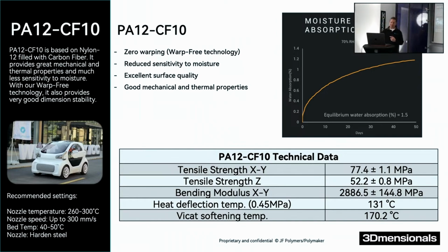So then moving down, then we have PA12 CF, which PA is a polyamide, and now we're getting into our nylon filaments. PA12 is also a CF10, so that's also a 10% filled nylon. Very nice material, performing very well. And if you compare PA6, PA612, and PA12, often customers say, what is the difference between these materials? And it's all about the amount of carbon atoms in the polymer chain. So 12 stands for 12 carbon atoms inside the polymer chain.